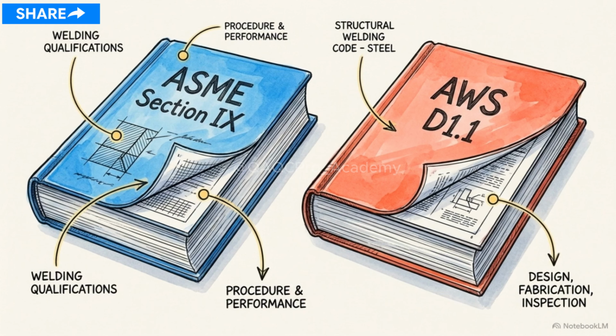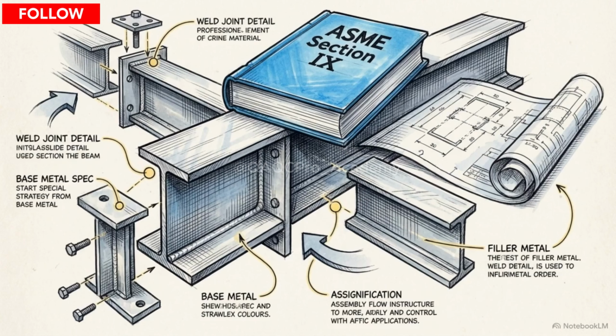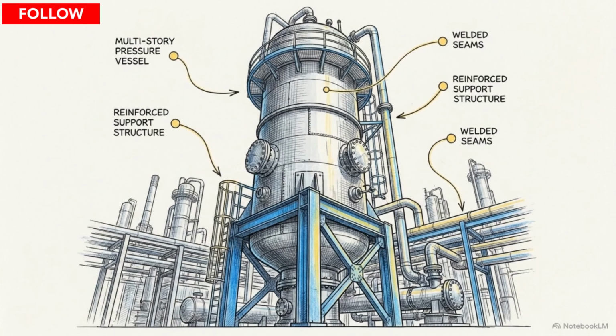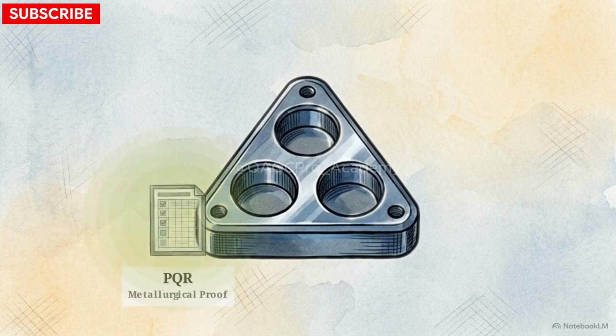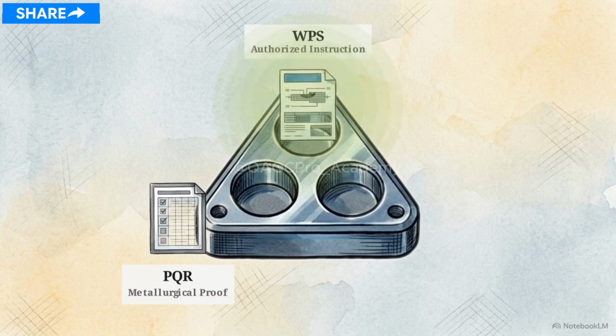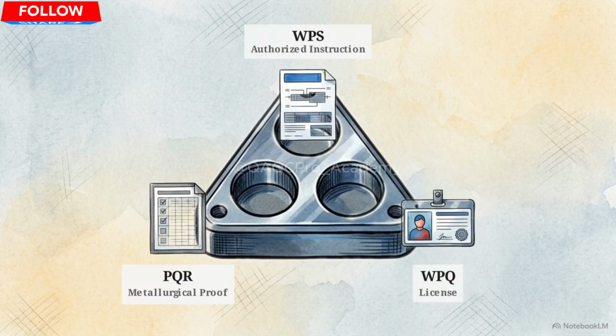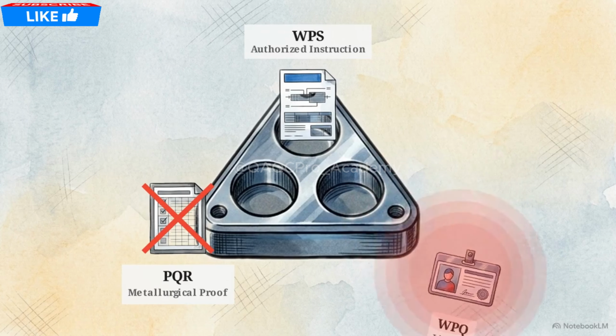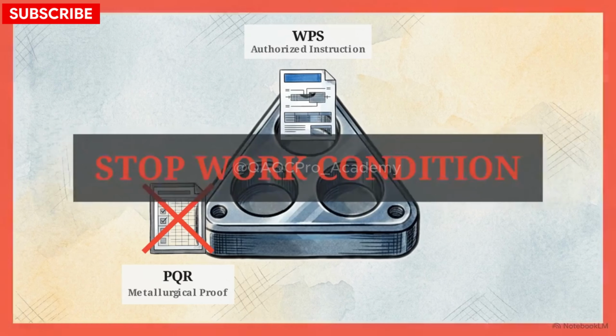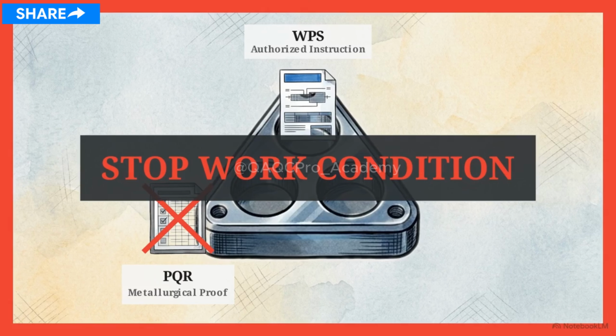Furthermore, these qualifications do not cross codes. A documentation package validated under ASME Section 9 for pressure vessels cannot be used to satisfy AWS D1.1 requirements for structural steel. This administrative continuity is just as legally binding as the metallurgy of the joint itself. The compliance triad relies on three components. PQR is the metallurgical proof, WPS is the authorized instruction, and WPQ is the license. Changing an essential variable breaks the proof, while a process lapse breaks the license. Either failure instantly triggers a stop work condition.